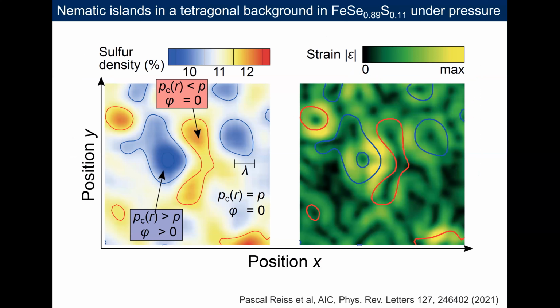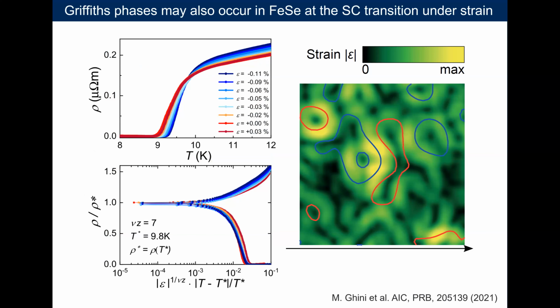And why will that occur under pressure? Well, we have sulfur for selenium substitution. That will cause a small inhomogeneity, but also under pressure, we can create a slightly different local strain. So those could be the conditions to create rare regions in a tetragonal system, and create this fluctuation and potentially the existence of Griffiths phases. We observed that this crossing also occurs under strain, in iron selenium in this case, between the superconducting to normal transition. So potentially the strain itself is a key parameter which could lead to the formation of these phases.